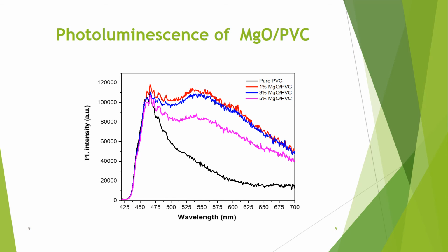The photoluminescence spectra of magnesium oxide PVC. The spectrum of pure PVC shows no emission peak. Besides, the other samples have a yellow emission band at 550 nanometers due to the transition between singly charged oxygen vacancy and the photo-excited holes in the valence band of magnesium oxide nanoparticles.